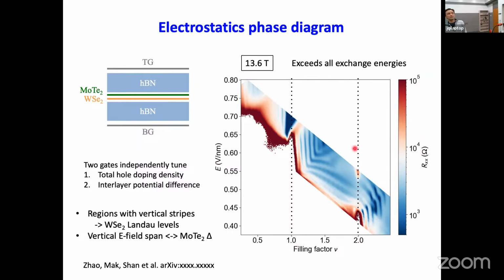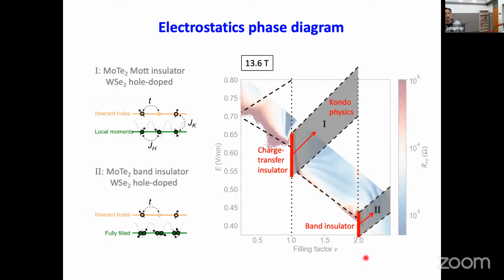Yeah, but I want to point out that you have this region with just vertical stripes, where you only have one Fermi surface, which is the tungsten Fermi surface. And then there's another region here around filling factor equal to 2. You also see the vertical stripes. So you can divide that into this line, and it looks a bit like the schematic that I showed you before. Here at filling factor 1, we start with a charge transfer insulator before band inversion, then we dope additional carriers into the tungsten. And then we only have one set of electric field independent cyclotron resonance in the system, right? And then this is starting from the band insulator at filling factor equal to 2.